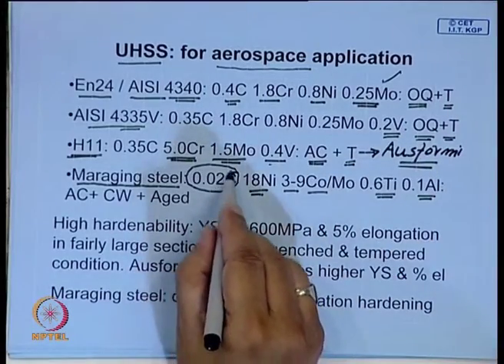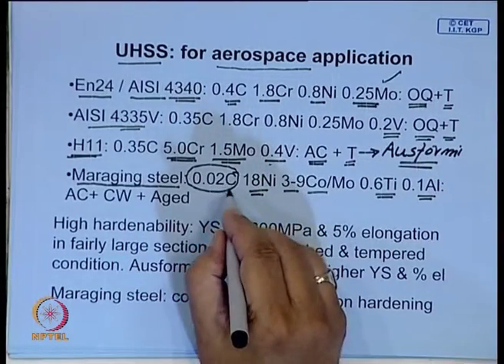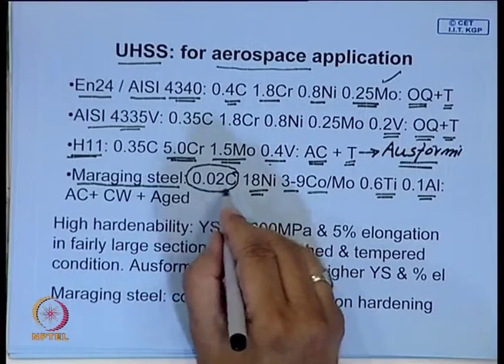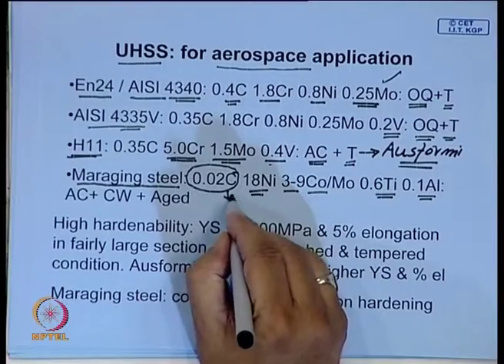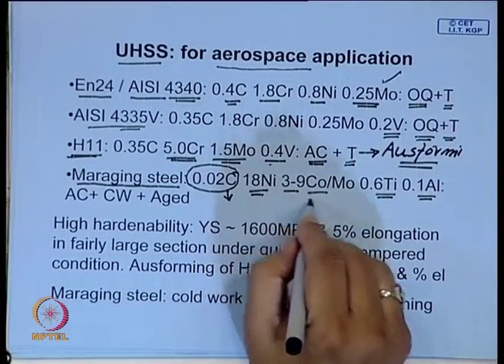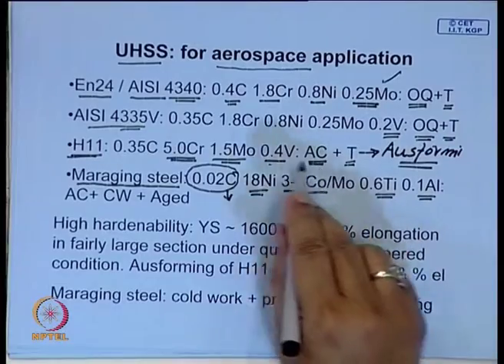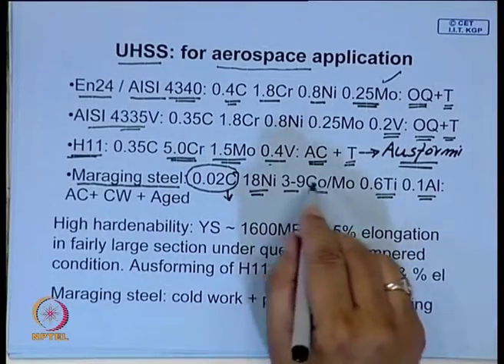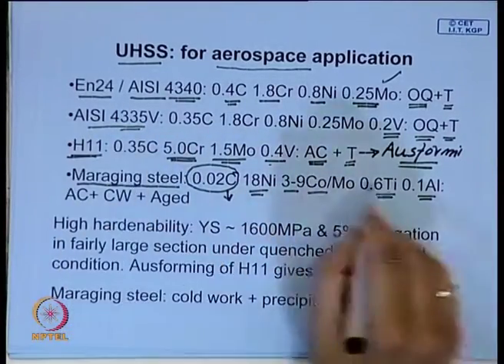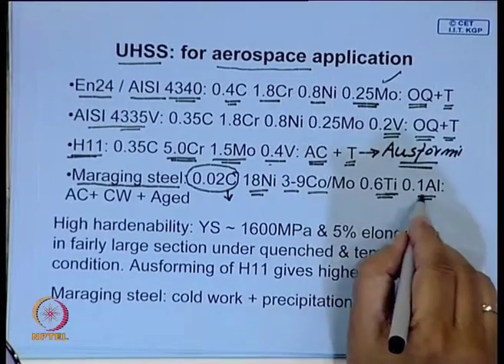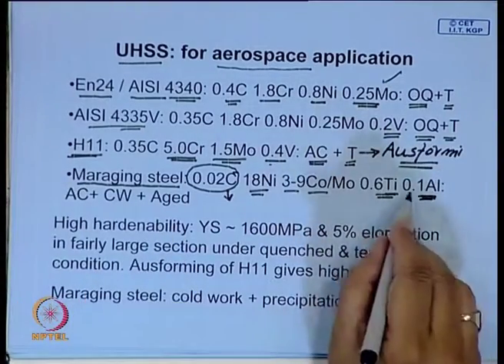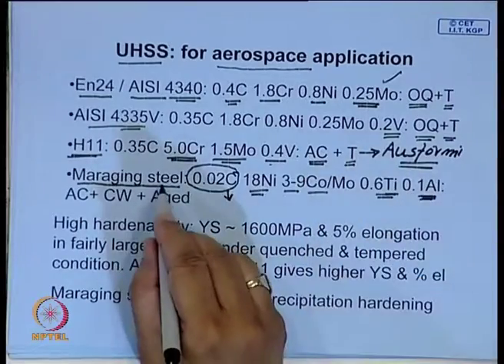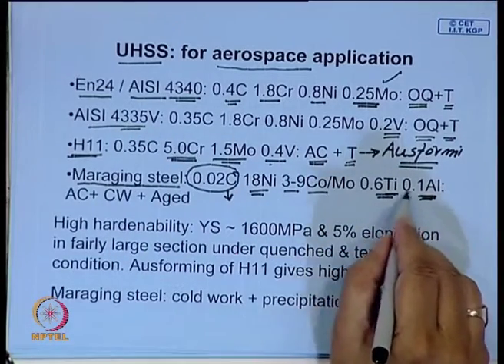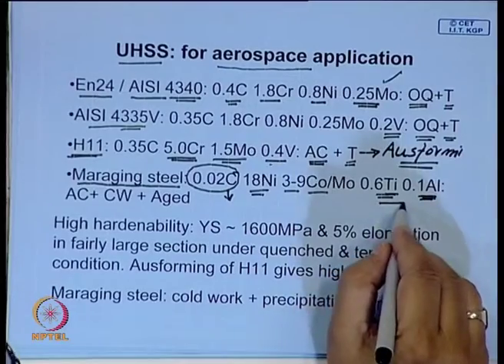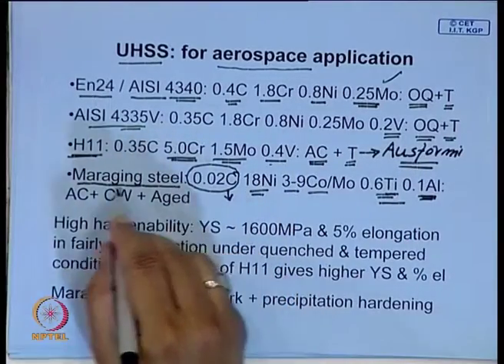The main thing is you look at that carbon content. Martensite is hard because of carbon, and if you reduce carbon to this level, definitely the martensite will be soft. This martensite you can cold work, so it may not have that high hardness, and it is aging, meaning when you age, these are the elements which develop some coherent precipitates in the matrix, and because of the formation of these fine precipitates, its strength goes up.